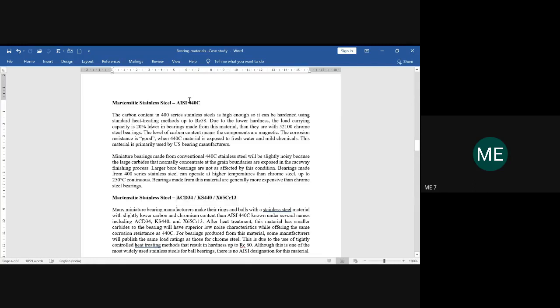So if it is across the 400 series in stainless steel, then you can consider that the carbon content in 400 series of stainless steel is comparatively higher. Since it is higher, it can be used for hardening. So you will do the hardening basically when you need a heat treatment process, right? And hence you can get a hardness value nearly to 58. In regular without heat treatment, the hardness of the stainless steel will be comparatively lower. And as a result, the load carrying capacity is 20% lower in bearings which are made by this material.